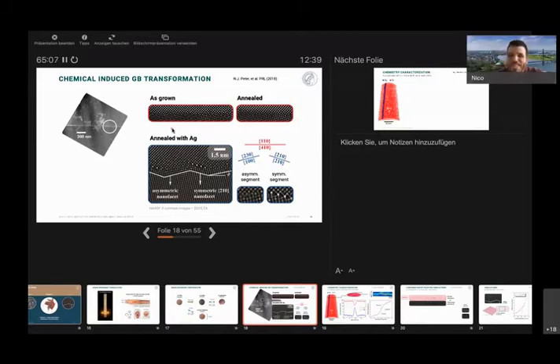Yes, thank you that the images look good, first of all. Second of all, I think you can, in an uncorrected microscope, if you choose the right zone axis, get some sort of atomic resolution, not in STEM maybe, but in TEM. Okay. So that should work. However, it depends on what you want to do with it. And TEM then becomes a different story because you would need to do image simulation because of contrast reversal. So there is a lot more things to take into consideration. Yeah. Okay. But if you have a good conventional TEM, I think in certain zone axes you can also get some okay image. Okay. Yeah.